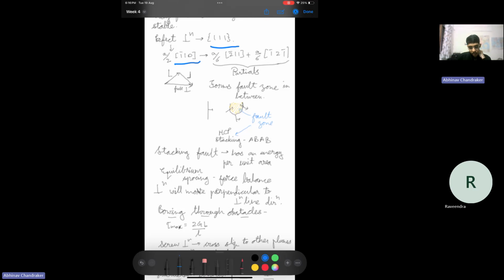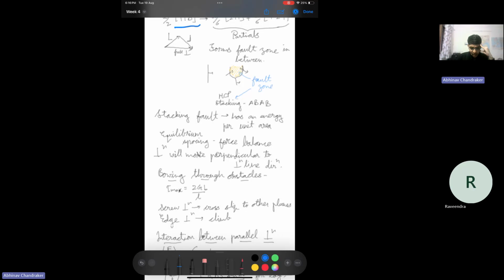So when it splits into partials, these two Burgers vectors a/6 <2 bar 1 1> are not going to lead to a slip to a position which is a lattice position, while a/2 [1 bar 1 0] will take it to a lattice position. That's why they are called partials. And when partials form, for example here, there are two partial dislocations, and they form a fault zone in between them, and locally the stacking changes. So if it was ABCAB, like as it is in FCC, locally it will become ABAB and so on. So locally you have HCP stacking coming in, and because there is a fault in the stacking, we call it a stacking fault.